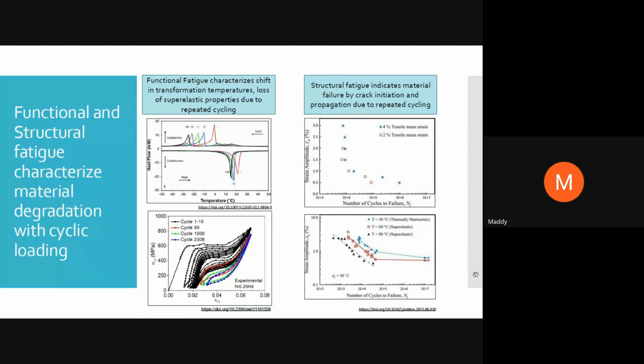So the chart shows your stress-strain response. And from cycle 1 to 10, you can see that that particular degradation is extreme. You can see how the degree of shift in the upper plateau stress is significant. But as you increase the number of cycles from 50 to 1000 to 2500, you can see that the shift, the degree of variation, has significantly decreased.